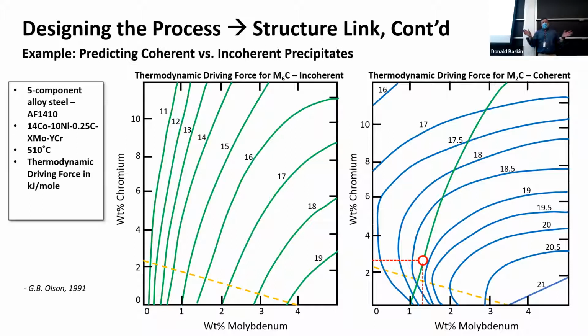Okay? They can grow and they can get soft again, but let's just say for now that they're just going to stay well dispersed and they're going to be tiny. What's called the thermodynamic driving force is what determines the size of these precipitates once they start to form. So at certain thermodynamic conditions, you'll get a few of them that are big. If the thermodynamic driving force is low, you get these big ugly precipitates that don't do that good of strengthening because they're overcoarsened. If the thermodynamic driving force to get these precipitates is high, then you get the fine dispersion of these precipitates, little tiny suckers growing in it, maybe only a couple nanometers wide, right? So Thermo-Calc will actually tell you what the thermodynamic driving force is for various different phases that are going to form in the material.